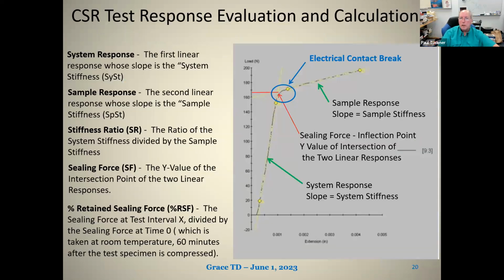So when you run the load deflection test, you get a response curve that you see on the right. The first part is known as a system response, and the second part is a sample response. The initial part is when you're compressing, you try to compress and deform the top shim, and this is what happens as the load increases before you exceed the sealing force. Once you exceed the force that the rubber is exerting on that top shim, you begin to compress the specimen at this point. So this gives you a different slope, and the inflection region or inflection point is the sealing force that you've overcome to get these two responses.